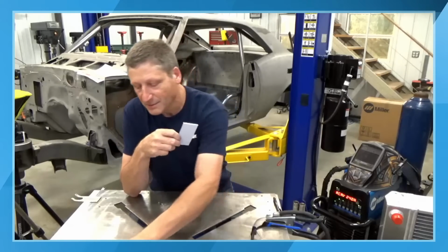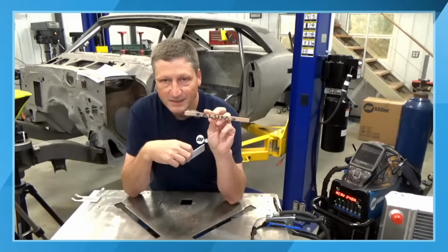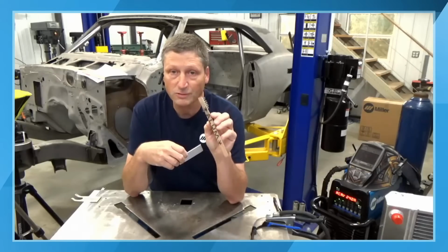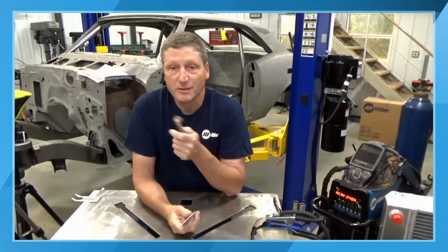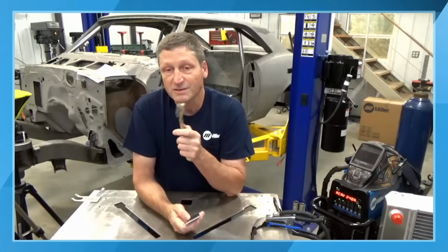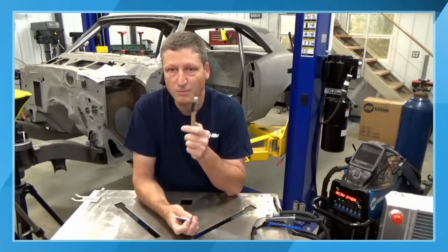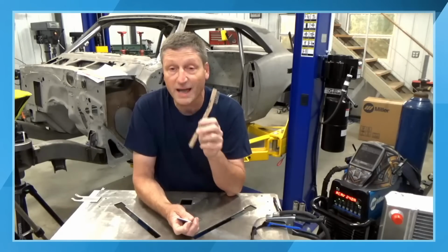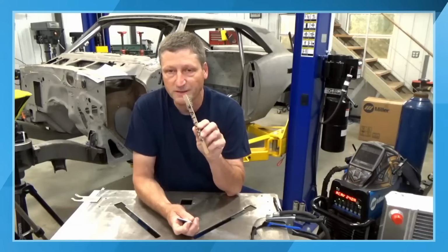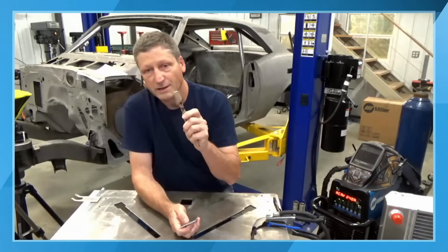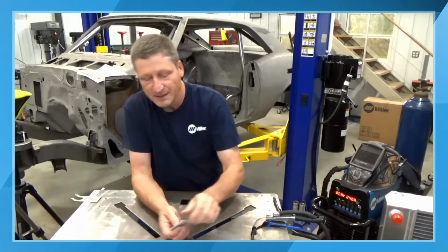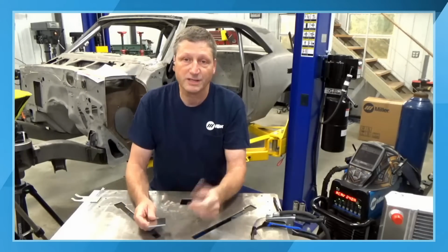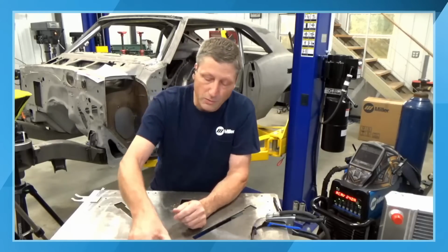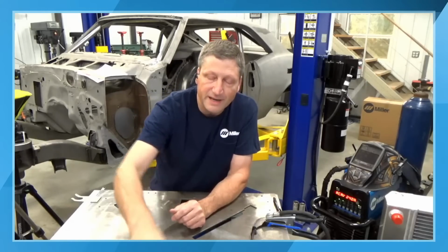That's using a dedicated stainless steel brush just for aluminum. If you've seen some of the previous Shop Talk Lives, especially the beginner welding aluminum one, they probably covered cleaning and prepping the aluminum quite a lot. So we wire brush it, and then a little acetone on a rag, or denatured alcohol also works really well. And clean that oxide dust off of that piece before you weld it.